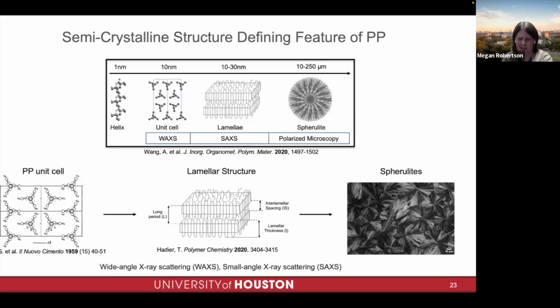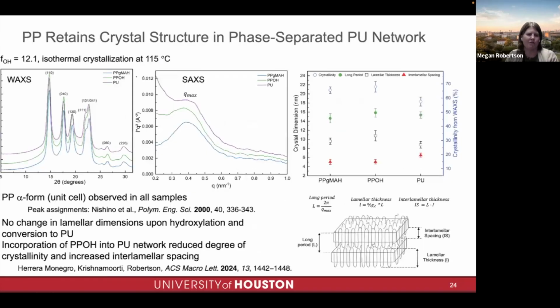And we can look at the length scales of polymer crystallization. There are multiple length scales. We can look at the unit cell. Those unit cells pack into lamellae, which are sheets, and then those sheets are arranged in a sphere-like structure shown here. And we can examine all of these through a combination of X-ray scattering and also microscopy. And so from the wide angle X-ray scattering, these peaks are characteristic of the polypropylene unit cell, which is the alpha form. And basically, we just see no change in the unit cell, even though we've taken our polypropylene and turned it into a polyurethane network.